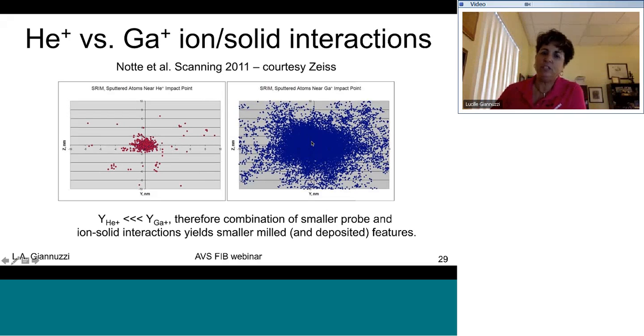The heavier gallium is going to generate a lot more recoil. This is going to generate sputtered particles from much further away from the center position. So assuming that you've got the same beam size between helium and gallium, you're going to be able to FIB mill a much smaller feature with helium than with gallium. Now combine that with the fact that the helium beam itself is going to be an order of magnitude smaller than gallium. With the combined fact that the sputter yield of helium is much lower as well as much more confined to the center point, you're going to be able to FIB mill much smaller features with the lighter helium than with the heavier gallium.